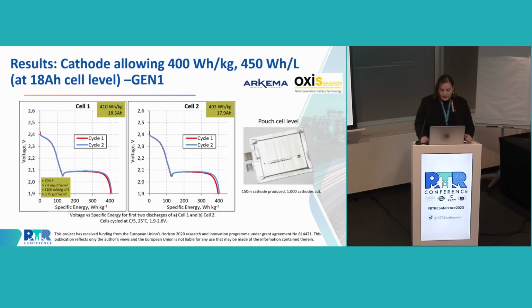If we go to the results in more detail, here I'm showing you the first KPI achieved with the help of the Arkema and Oxis Energy companies. Here, we were able to obtain a cathode with more than 70% sulfur utilization, reaching between 400 and 410 watt-hour per kg. We upscaled this cathode up to more than 100 meters, and it was ready to be used.